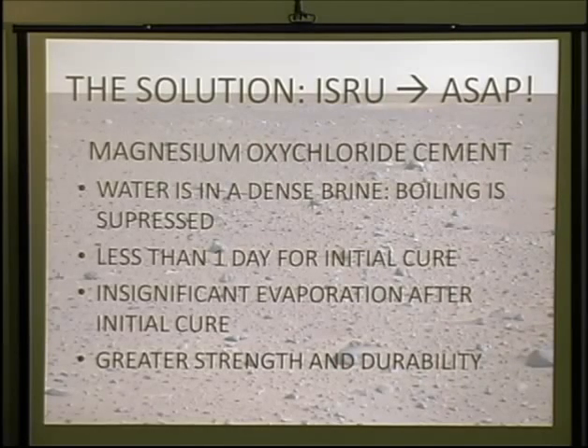There's another option, magnesium oxychloride cement. It's a magnesium-based cement composed of magnesium oxide, a powder here, magnesium chloride, a very common type of salt, and of course, plain old water. And the advantage is that the water in here, while it does require water to cure, the water is mixed in with the magnesium chloride salt in a dense brine, which will not boil at Martian atmospheric pressure. It sets up and cures in less than a day, after which the water is locked up in the crystal structure and will not evaporate.